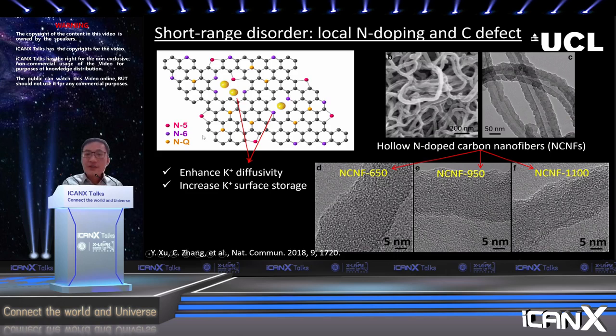The nitrogen doping usually exists in 3 different forms: nitrogen 5, nitrogen 6, and then nitrogen Q. Nitrogen 5 refers to the nitrogen in a 5-member ring, which mimics the environment of pyrrole. And nitrogen 6 refers to the nitrogen, the purple ball here, in the 6-member ring, which mimics the pyridine environment. And nitrogen Q is the orange balls right here, which mimics the graphite environment.